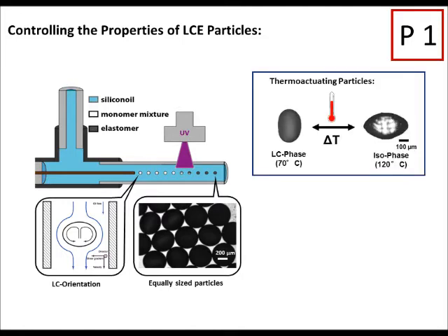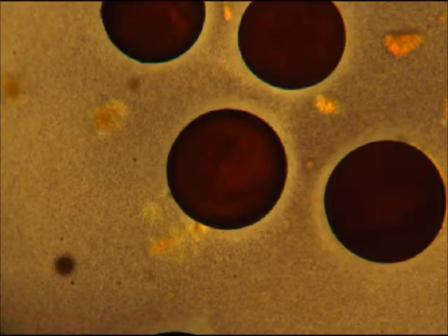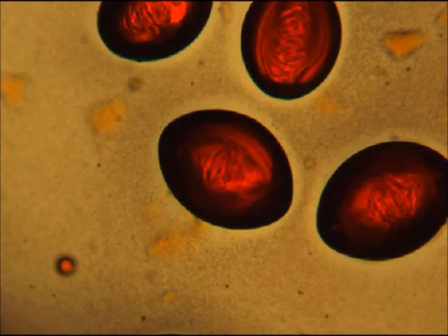Using this microfluidic setup, particles showing a strong and reversible actuation were obtained. And by introducing azobenzenes to the LCE system, we also succeeded in the preparation of photoresponsive particles, which show a full actuation of up to 24% in less than 10 seconds during irradiation with white light, as it can be seen in this video here. This deformation is reversible either by keeping the particle in the dark or by irradiation with red light.